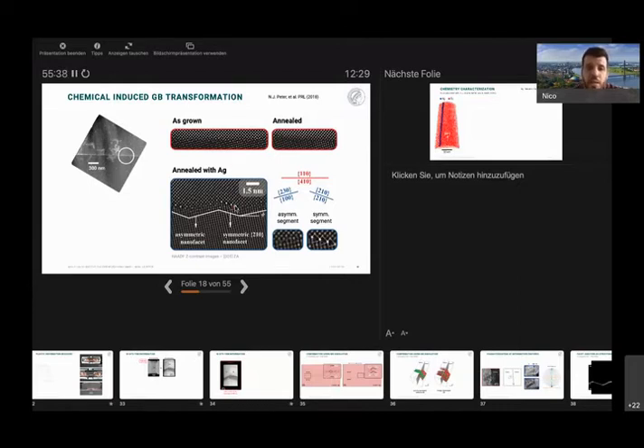I don't think it's too much a function of the solute that you have, because the solute mostly goes to fairly defined positions, and most likely for the 210 boundaries, this is the CSL position, this bright position, for many elements that has been shown by now. So I think this is not really the determining factor. I would rather say the grain boundary is the point which makes the angle. Is that okay?